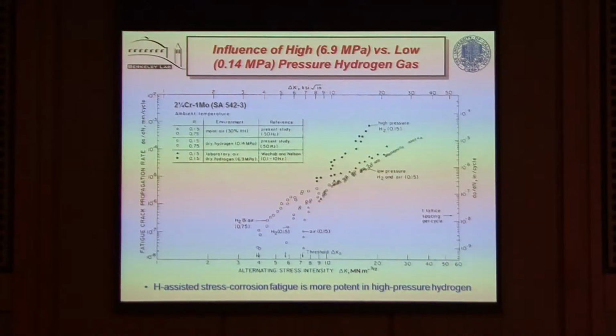7 megapascals. The facilities here at Kyushu can do tests at 120 megapascals. Now, there's lots of data in the literature on hydrogen embrittlement and how hydrogen affects crack growth, but there's very, very little data at these very, very high pressures. So from an engineering perspective, information on how cracks grow in high-pressure hydrogen, which reflects the reality of a hydrogen economy, is critical, and that's taking place here. I think probably this is the only place it can take place. There are very few facilities outside of Japan.